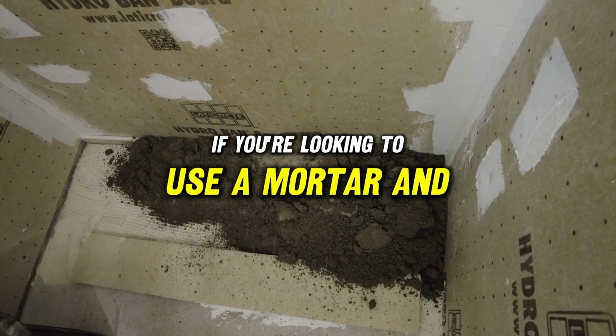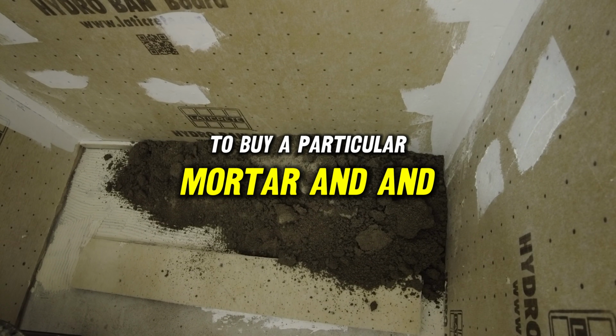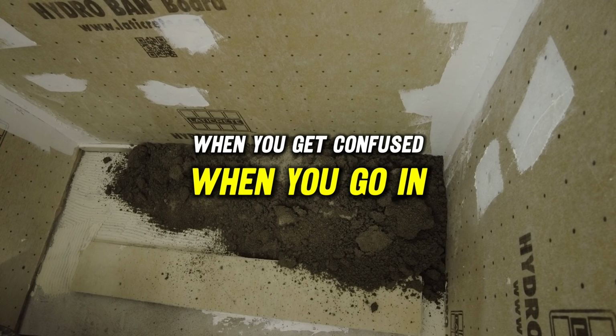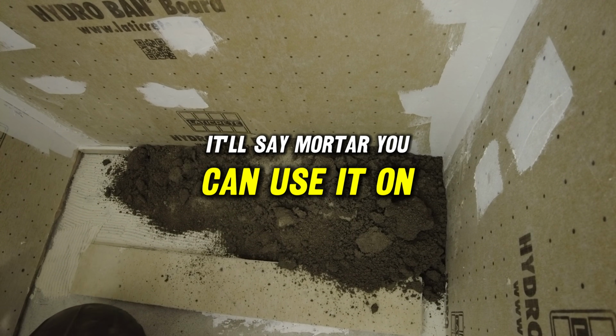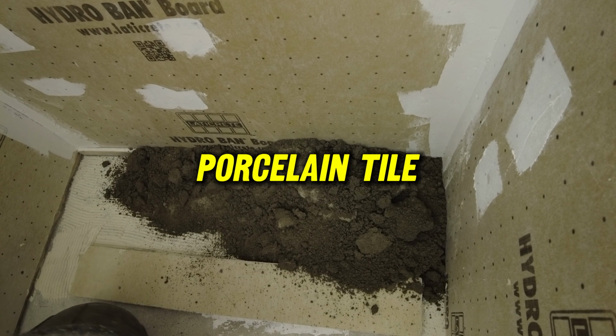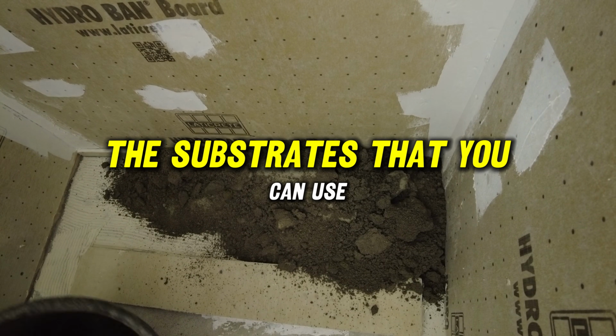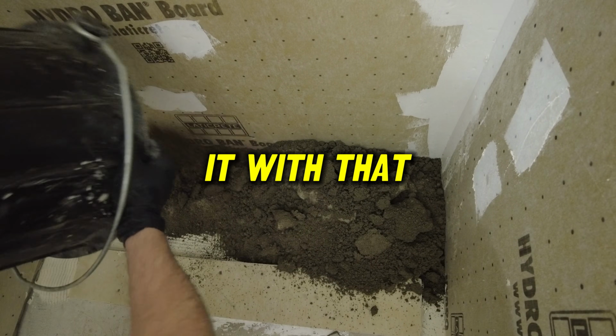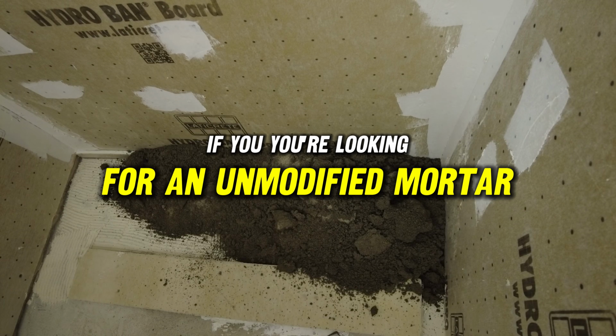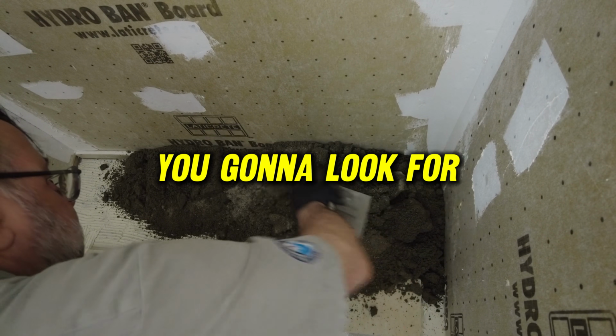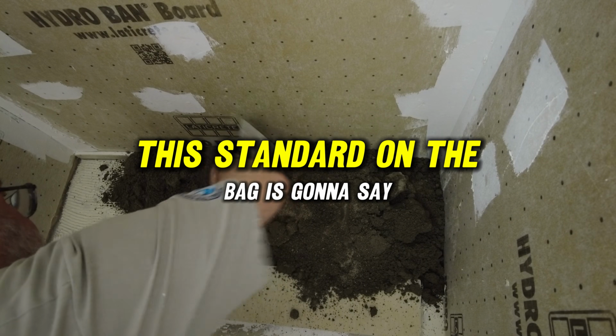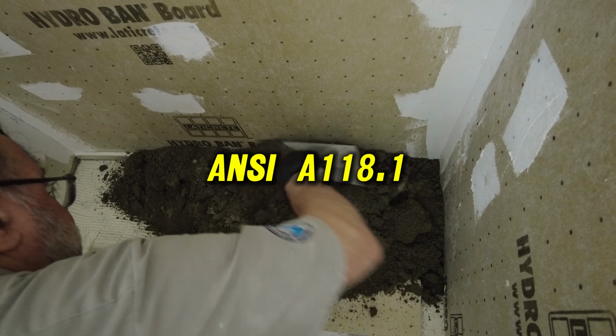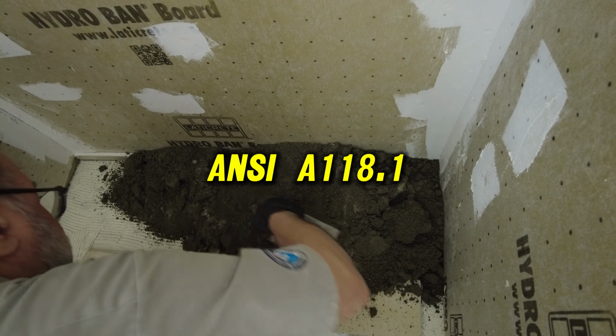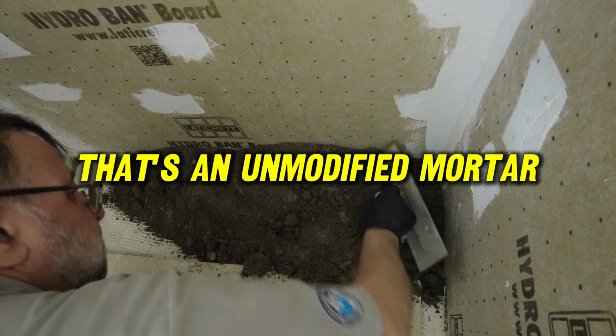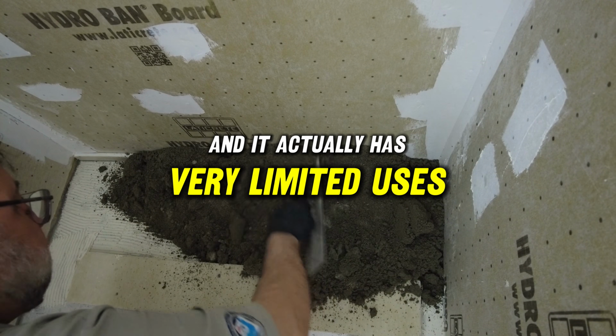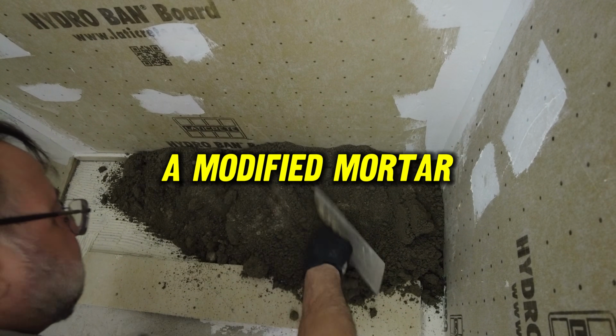If you're looking to buy a particular mortar and you get confused when you go in the store, it'll say the mortar to be used on plywood, used for ceramic tile, for porcelain tile, and list a bunch of the substrates that you can use if you mix it with this or that. If you're looking for an unmodified mortar, because that's what you've been told to use, you're going to look for this standard on the bag. It's going to say ANSI A118.1. That's an unmodified mortar, and it actually has very limited uses. Most people will use a modified mortar.